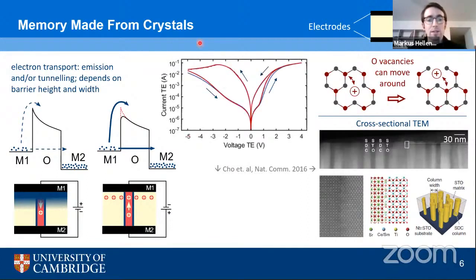So this seems to work fairly well. I measured these current versus voltage curves in our lab the other week, and this reflects exactly what I tried to point out. If we start with 0 voltage at one of the electrodes and increase the voltage, we get some current, and at the same time we accumulate positive charge at the other side of our little device. So when we go back, now we have this accumulation, the barrier is lower, and for the same voltage, we now get a higher current than before when going back down to 0.